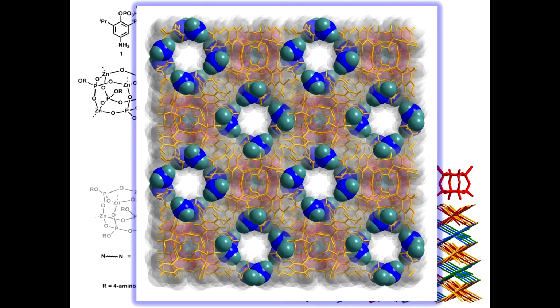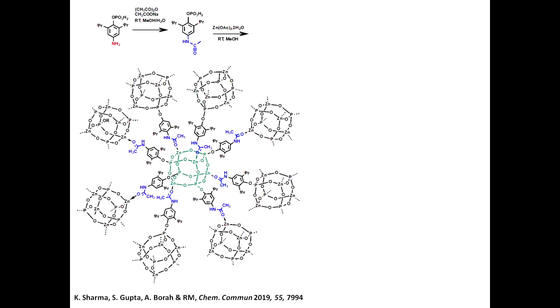So essentially I get a structure where the channels are no longer hydrophobic, they become hydrophilic and basic. The first ever example we could demonstrate was carbon monoxide and carbon dioxide adsorption on this. So essentially you have a channel which has been decorated with NH2 groups. So she went actually one step ahead.